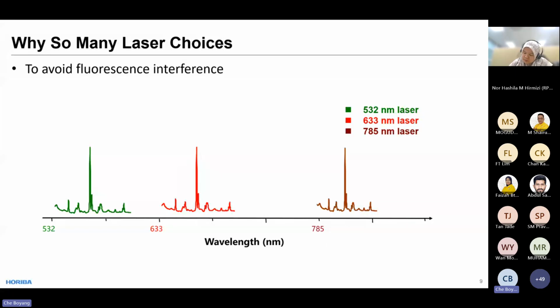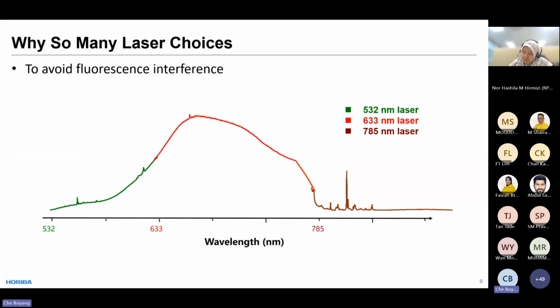However, in real life, what we usually get is this kind of result. You will see a very strong background under the green and red lasers, and this background is caused by fluorescence. Raman is a relatively weak signal, but fluorescence is quite strong, so your fluorescence background will cover your Raman peaks. You will not be able to observe the Raman peaks if the fluorescence is too strong. To solve this issue, we suggest using a laser with a higher wavelength, closer to the NIR. When we use this 785 laser, you can see the fluorescence is reduced, and we can see more Raman signals from the sample.